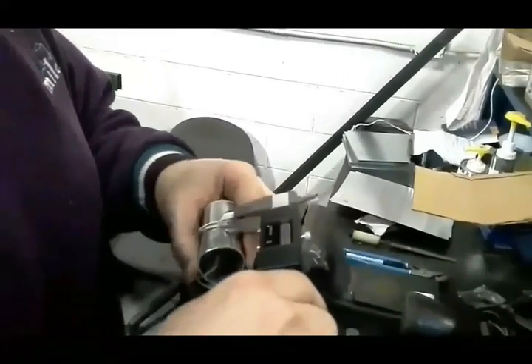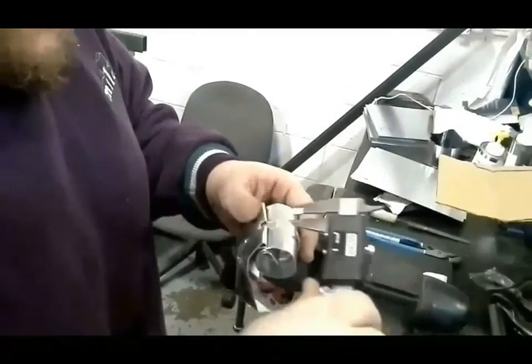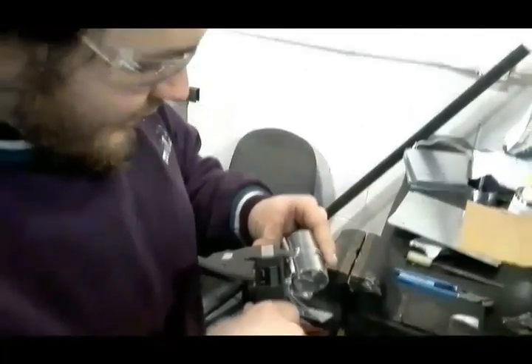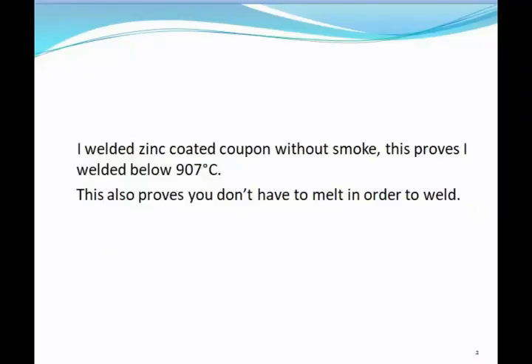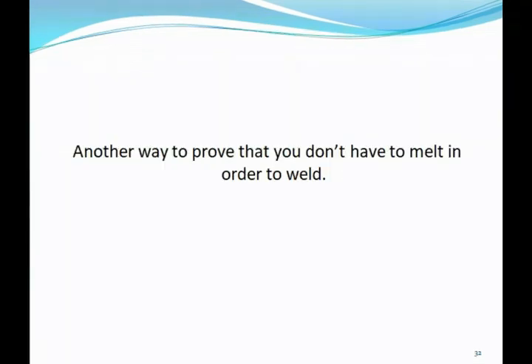First weld, 6.01. Second weld, 5.88. And your third weld, 6.03. I welded zinc-coated coupon without smoke. This proves I welded below 907 degrees Celsius. This also proves you don't have to melt in order to weld.